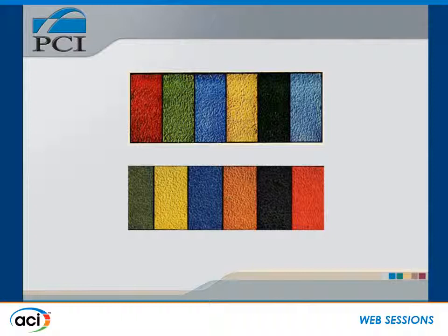These are some of the vitreous and ceramic aggregates that were used. You can see that they had some very bright or a little duller colors. The ceramic aggregates were made from high-grade clays and other ceramic raw materials by processes similar to those used in producing pottery and chinaware. The vitreous aggregates were made with materials and by methods similar to those used to produce porcelain frits or glass. While the colors of ceramic aggregates are bright and clear, they are characteristically soft in color. Vitreous aggregates are distinguished by their greater luster and brilliance than the ceramics. Certain colors can only be produced in the vitreous type of aggregate.